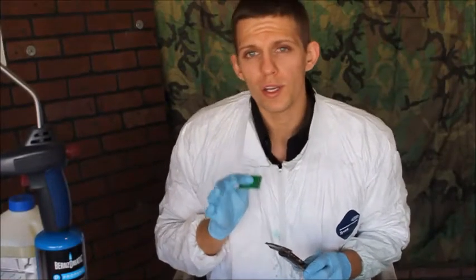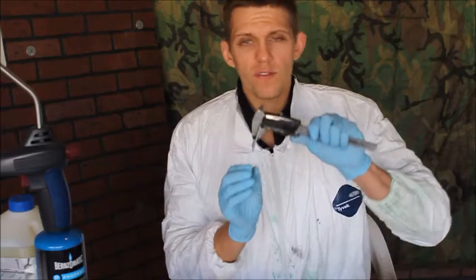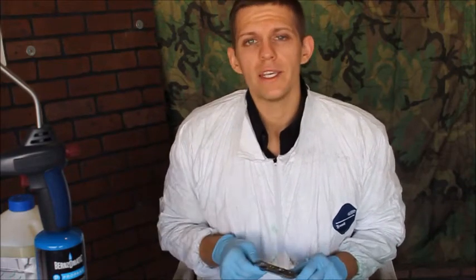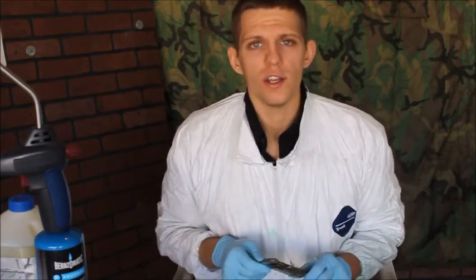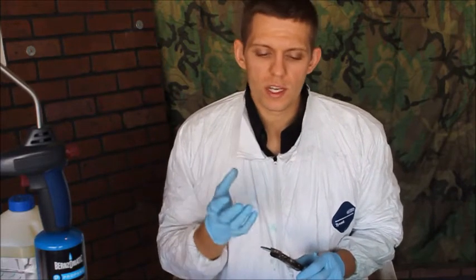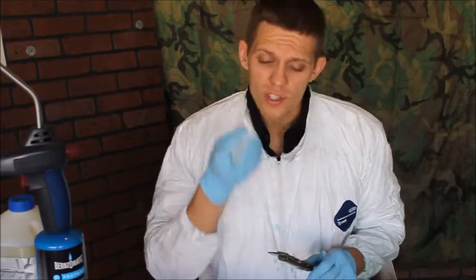One thing that is very important when it comes to testing surface coatings is how thick the coating itself is when added to any surface. What we did was we took a very fine caliper measure and measured every metal piece to include our aluminums and steels, and we took two measurements from millimeters to include inches. Now what we have noticed on every single coating, whether it is one layer or three layers, you only get thousandths of an inch thickness on any surface. The reason is that once sprayed, it goes deep into the pores and sinks inside, not sitting on top of the surface like most epoxy coatings, which tends to make them thicker.